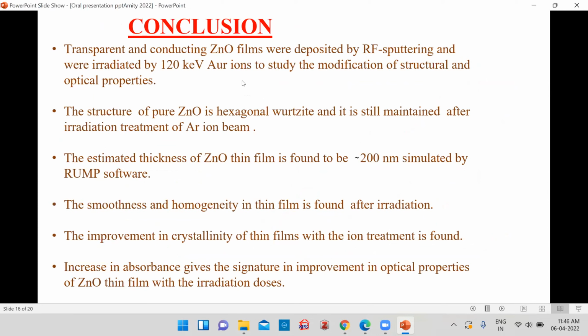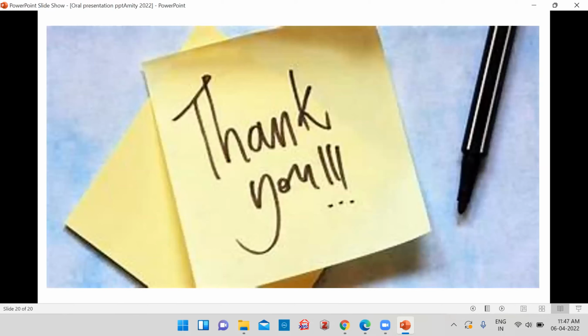These are the conclusions of the work. We have synthesized the ZnO thin films by RF sputtering, then irradiated with 120 keV ion beams. From the XRD, we get the structure of pure ZnO, which is hexagonal wurtzite. The estimated thickness of ZnO is approximately 200 nanometer. Smoothness and homogeneity are found after the irradiation with the help of FESEM images. Improvement in the crystallinity of thin films with the ion irradiation is found with Raman spectra. Increase in the absorption gives the signature of improvement in optical properties with the ion doses. These are the references. Thank you.